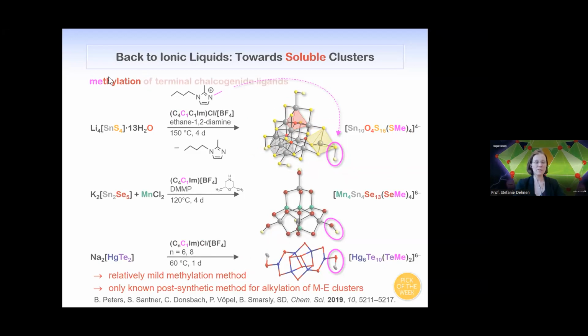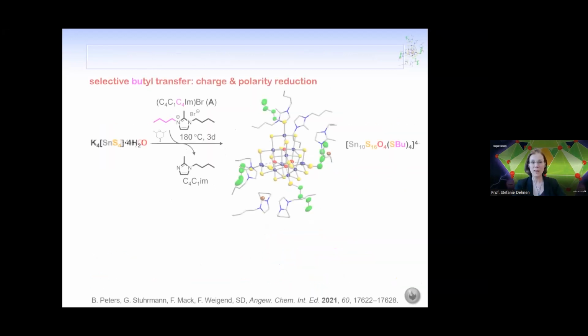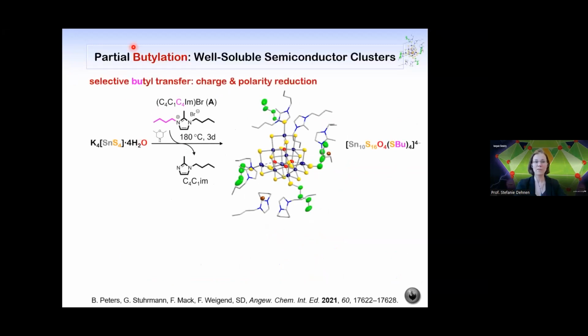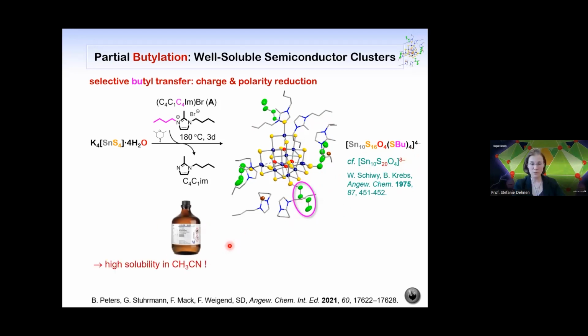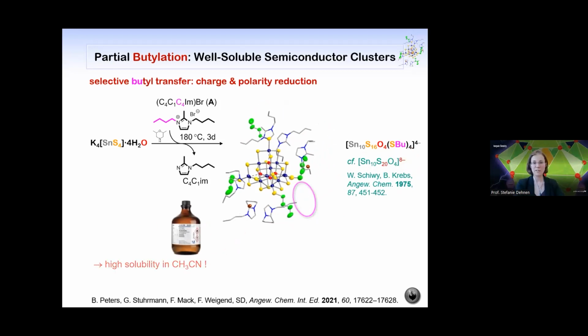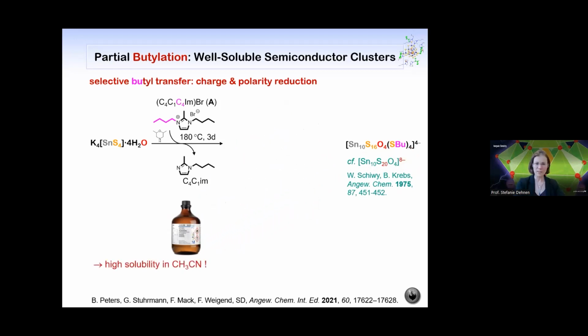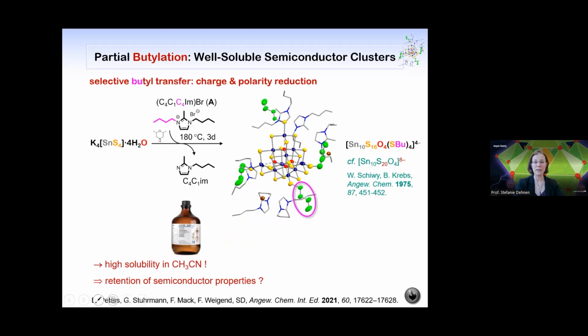So we thought of doing the same thing with selective butylation, and for this we needed a symmetrically substituted imidazolium cation, because the butyl methyl one would selectively strip off the methyl group. Here it doesn't have any choice, and so the butyl groups go on the cluster, thereby reducing the charge from a naked cluster that has been described many years back from 8- to only 4-. And with the butyl groups on it, it is well soluble even in acetonitrile, which was unique for this kind of cluster materials.